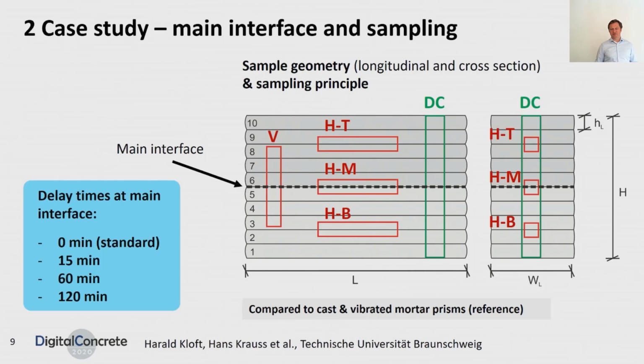Afterwards, we took prisms to investigate the mechanical performance. On the one hand, we had the main interface contained in the prism HM, horizontal, from the middle. Here, the main interface was allocated parallel to the long axis, whereas in the vertically taken prism, the main interface was allocated perpendicularly to the long axis. And in addition, we had here and here taken prisms with standard interfaces exactly in the middle of the prism.